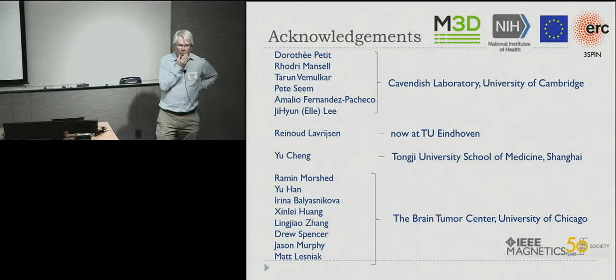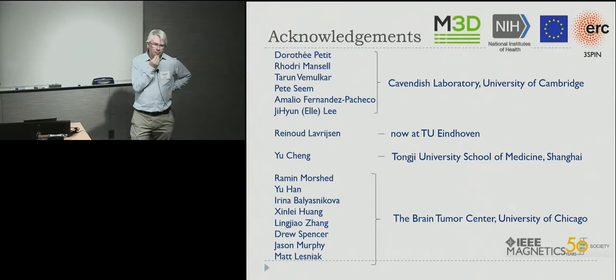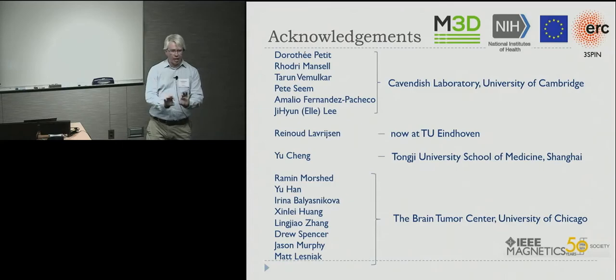So you have shown that these particles in magnetic fluid have planar dimensions like 2 micrometers and are much thinner. How do you manage to do that? How do you get rid of the substrate on which you deposit samples? So you put a release layer. Before you put the magnetic stack, you put aluminium as the very bottom layer, and aluminium can be dissolved in alkali. So you then do the full lithography, as if you're making spintronic devices. But as a final step, you put in an alkali, you dissolve that bottom aluminium, and the rest then floats off.